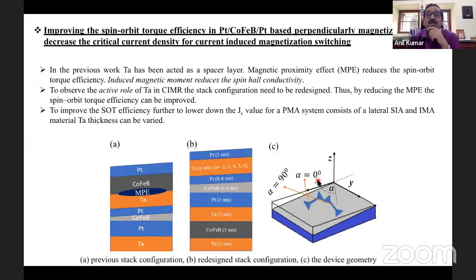Maybe I will just conclude with one more transparency. So this is the structure that we were looking at. Now what we did was we started putting a very thin layer of platinum and a thicker layer of tantalum on top of it. There is a reason. When you pass electrical current through this, the platinum has got a positive spin Hall angle and one type of electrons get accumulated. And when you have another platinum layer on the top, the opposite type of spin gets accumulated and they can cancel each other. So we wanted to put a material whose spin Hall angle is just opposite to the platinum, which is tantalum.